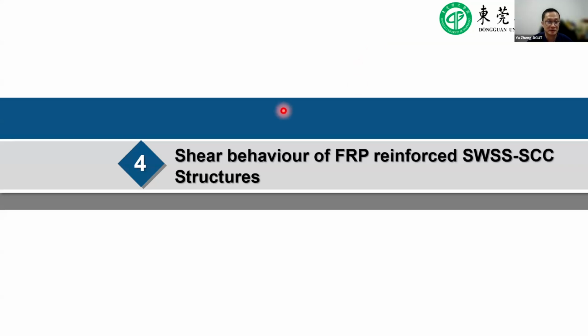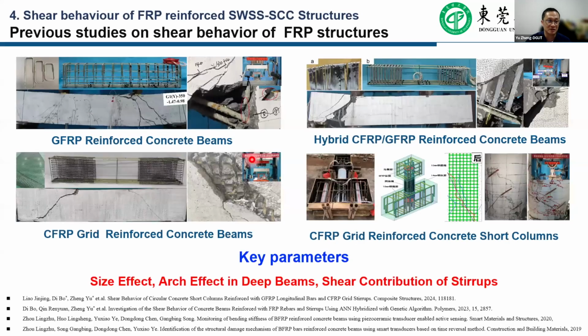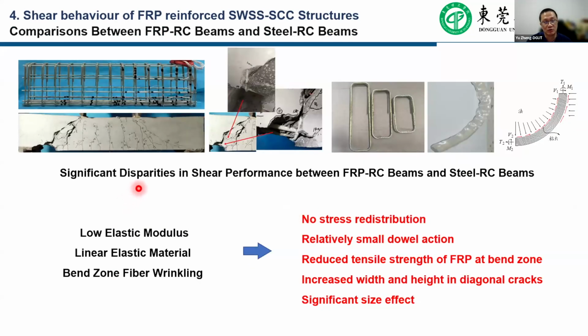The fourth part of our study, which is also the focus of my research, is the shear behavior, especially the shear behavior of FRP reinforced seawater and sea sand self-compacting concrete structures. We developed a quite comprehensive experimental study, which will not be discussed here, including GFRP reinforced concrete beams, hybrid FRP with GFRP and CFRP, and the FRP grid. We published several papers to investigate the size effect, the arch effect in deep beams, and the shear contribution from the steel stirrups, and those have been widely reported. There are significant disparities in the shear performance between FRP reinforced concrete and steel reinforced concrete.